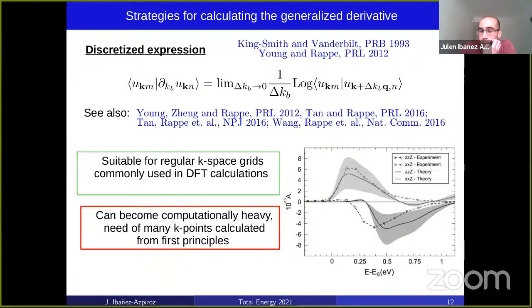In the literature, there have been a number of proposals. A popular one, adopted by the group of Andrew Rappe and among others, has been to use discretized expressions for the derivatives using finite difference formulas. And this approach is very suitable for regular k-space grids that are commonly used in density functional theory calculations. Now, this technique has been successfully applied to a number of materials.